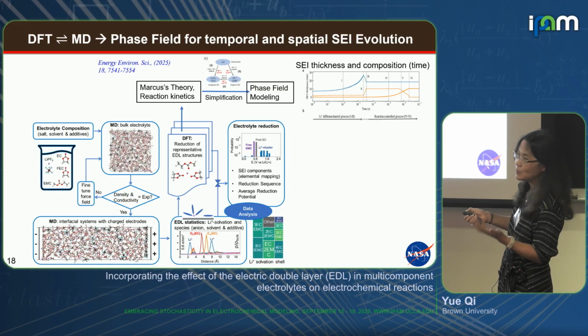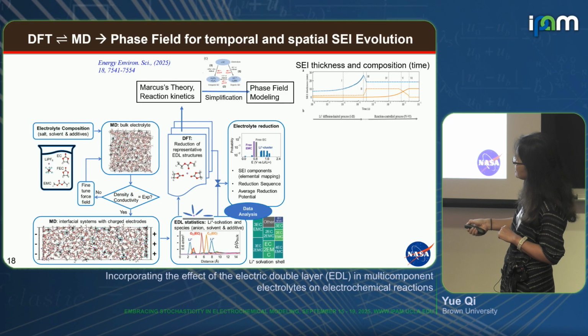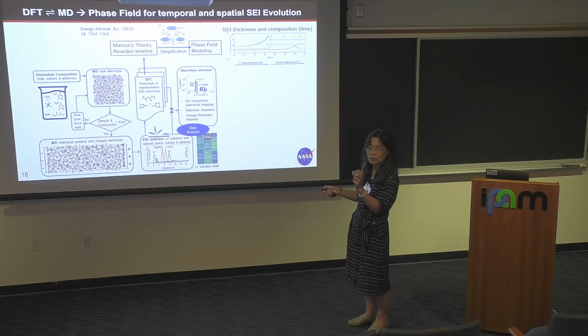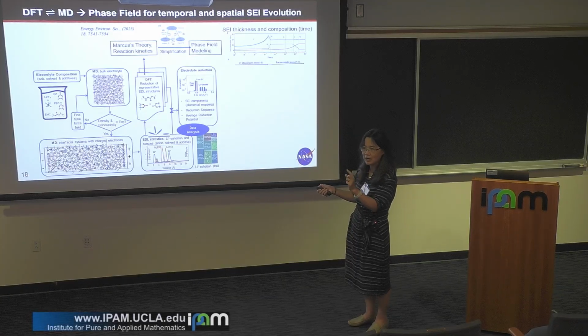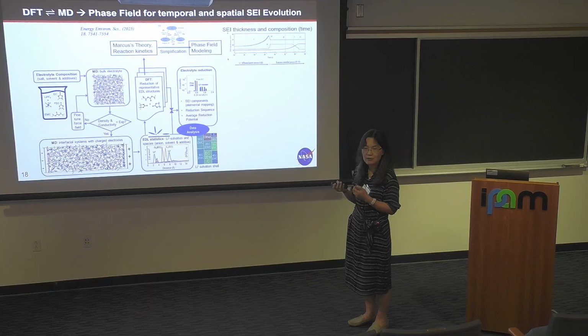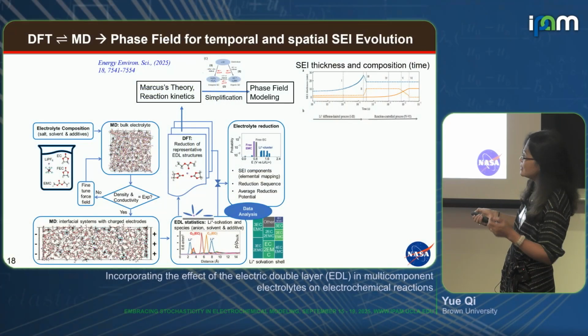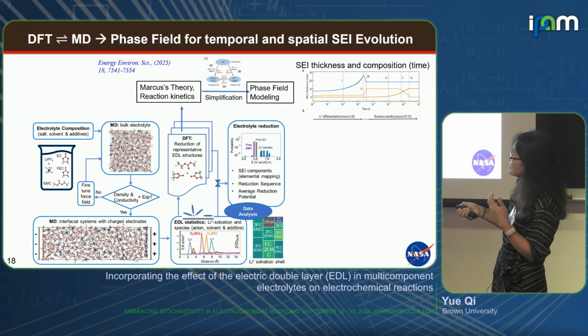So we'll do classical MD simulation, make sure we can recover the bulk properties, and then we subject it to two slabs. We use constant charge just for quicker calculations. And we want to see what comes to this interface, what are the probabilities for all these clusters. One thing you need to know is that these molecules' reduction voltage increases dramatically when they're next to a cation. EC reduction potential, probably you calculated 0.6 eV, but if it's next to a lithium ion, it becomes 1.6, something like that. So we really need to look at whether these solvent molecules are bonded with lithium or not. We calculate their probabilities around this lithium, and then we calculate their reduction reactions.